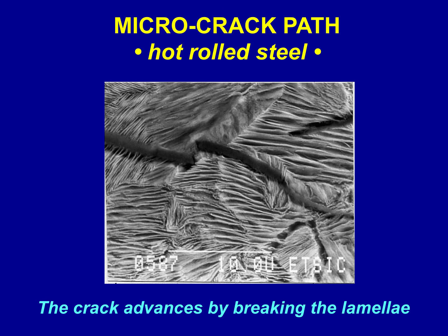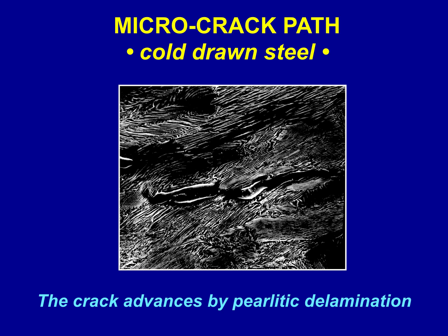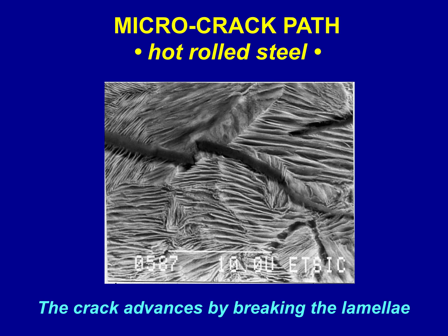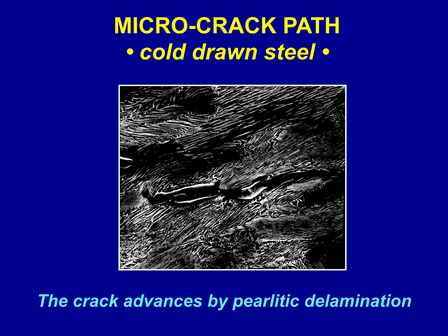With regard to microcrack paths in the hot-rolled steel, the crack advanced by breaking the lamella, but in the cold-drawn steel, the crack advanced by pearlitic delamination. Going back, breaking the lamella means a mechanism of the hydrogen-assisted cracking by tearing topography surface, but in the case of cold-drawn steel, it could be hydrogen-enhanced delamination or decohesion.